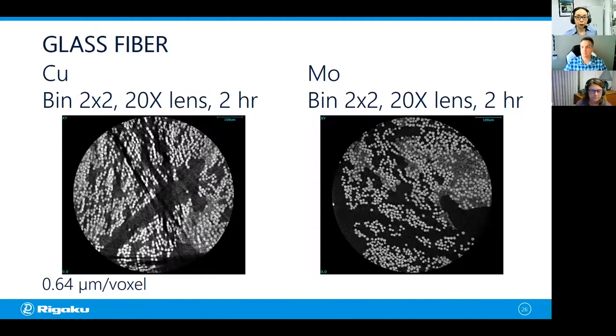Now, you might be wondering, if you're using almost monochromatic radiation, why would you get beam hardening artifacts? They happen only when you use continuous radiation. Well, this is the key: it's almost monochromatic. So when you use copper characteristic radiation, the majority of the radiation that you're using is 8 keV copper characteristic radiation. But there is a background, which is the Bremsstrahlung radiation that has a wider range and usually higher energy than copper characteristic radiation. So when the copper 8 keV X-rays cannot get through the glass fibers, that higher energy Bremsstrahlung background radiation becomes the main X-rays you're going to count. And that's where the beam hardening comes from.